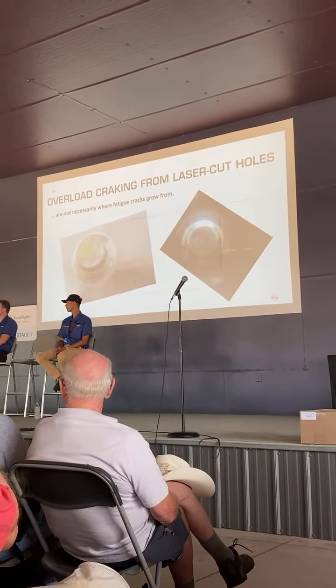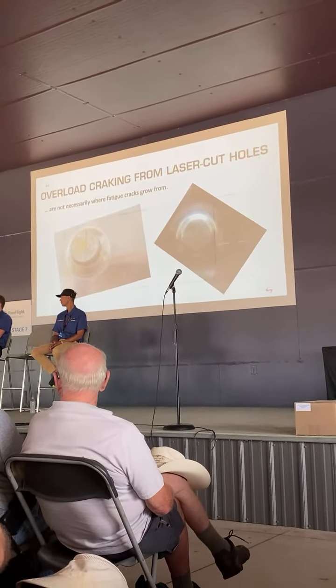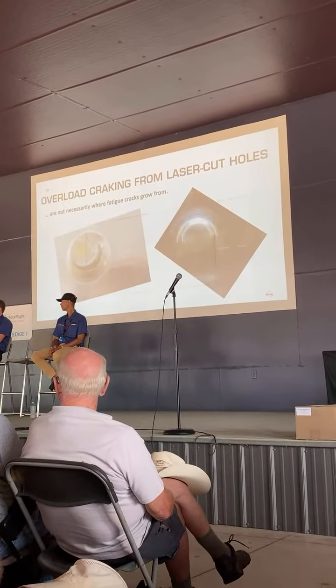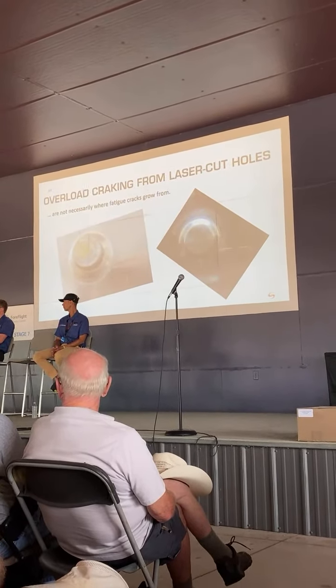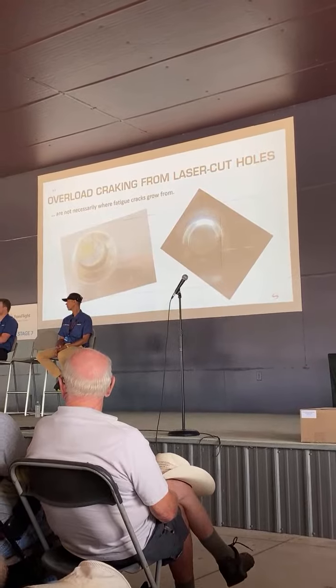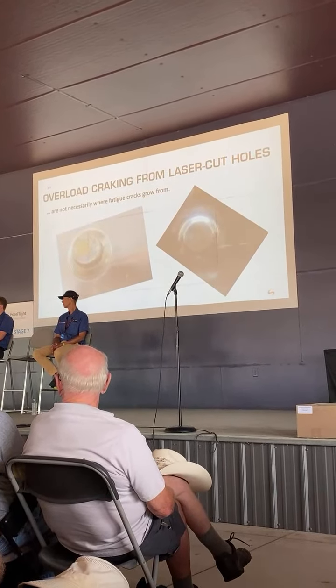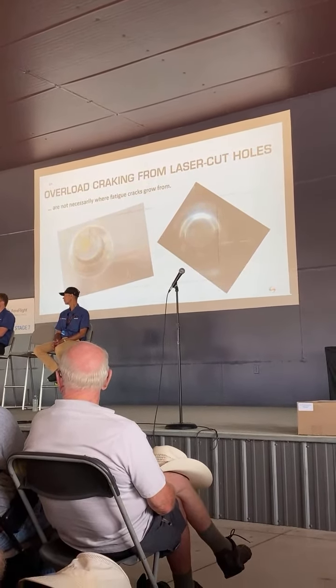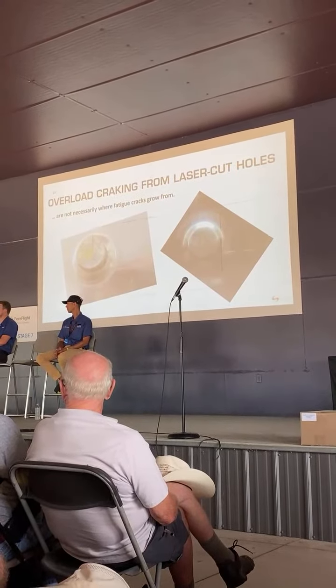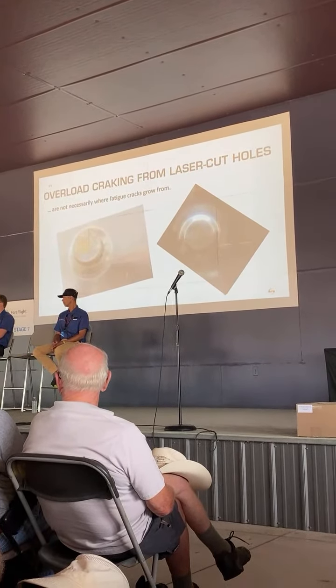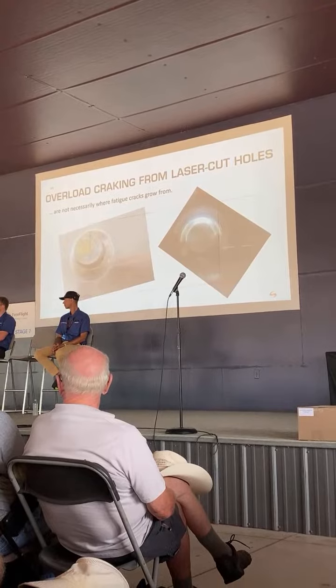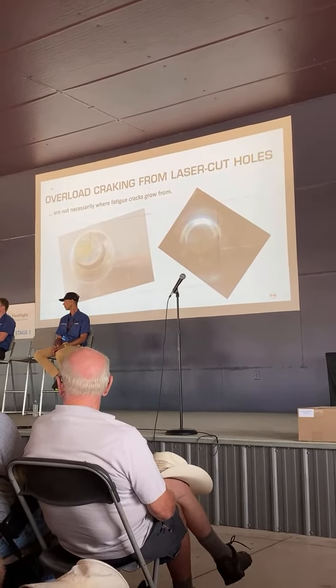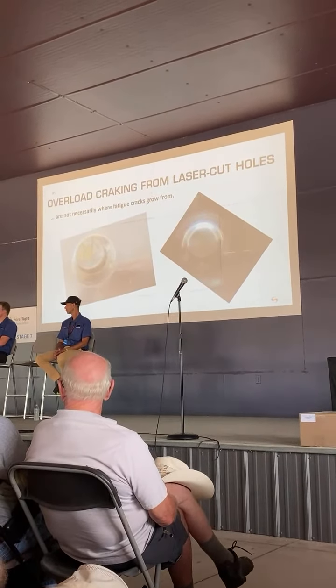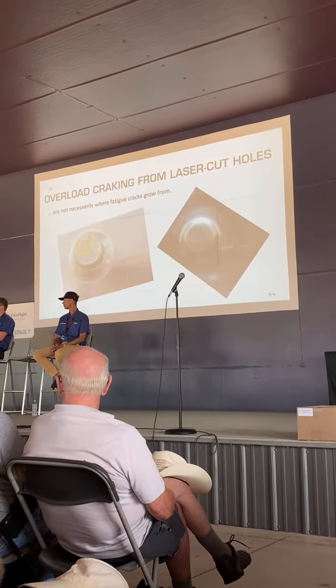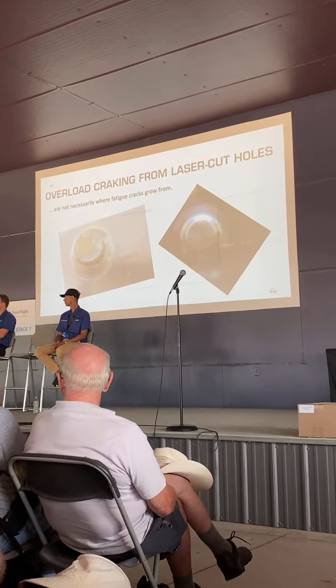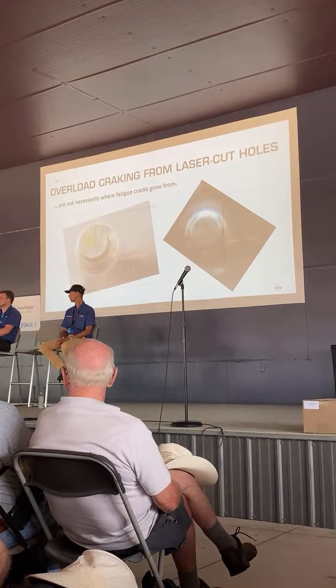And as a result, they thought that they had a structure that lasted a lot longer than it did. But the reason was they had those compressive residual stresses at the end of the crack, and they weren't overcoming them with the one pressure cycle. In our case, these tears, we believe, do have this compressive residual stress. And so it takes quite a high stress to overcome that residual stress into the crack. And that's why that crack isn't propagating. But we don't know that for sure yet.